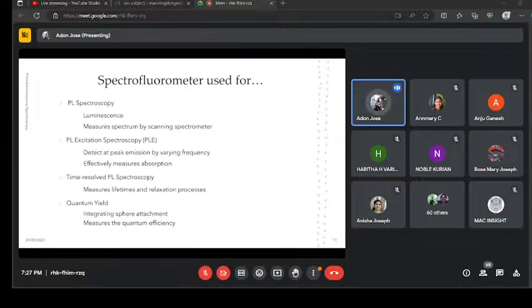So we can obtain the luminescence spectrum. Then we can also get data from excitation spectroscopy. And some advanced spectrofluorometers have time-resolved PL spectroscopy, which usually measures the lifetime and the relaxation process of a luminescent material. And some arrangements, such as an integrating sphere attachment attached to the spectrofluorometer, can usually record the quantum efficiency of the luminescent material.